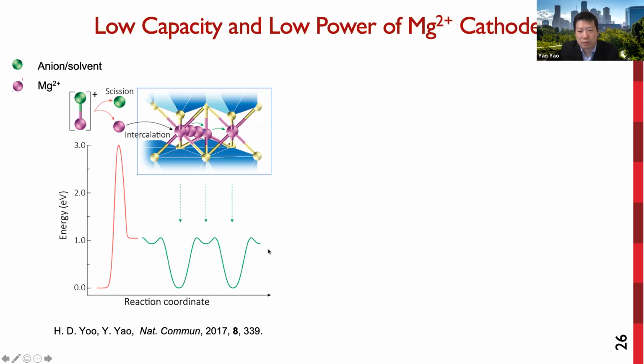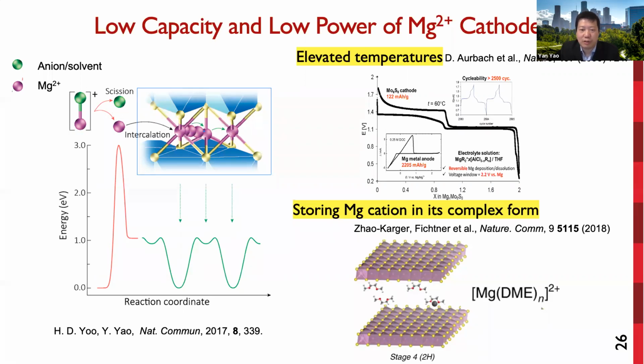So there are two approaches to address these challenges. The one is to cycle the battery at elevated temperature. For example, at 60 degrees C, the Doron Aurbach group has shown that Chevrel phase can reach theoretical capacity. The other approach is storing magnesium ions in their complex form, such as using DME molecules to solvate magnesium ions. So both approaches have disadvantages because elevated temperature would require a heater, which is not very practical. Storing complex ions would lead to a limited cycle life caused by volume change due to co-insertion of the bulky solvent molecules. So therefore, the cathode materials require a new reaction mechanism to support fast magnesium 2+ storage.